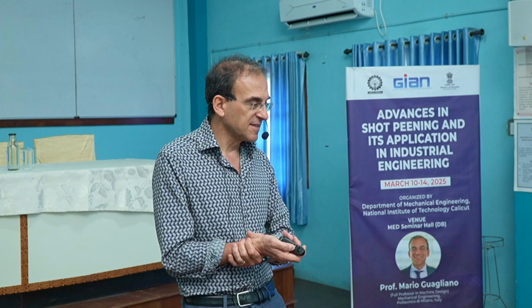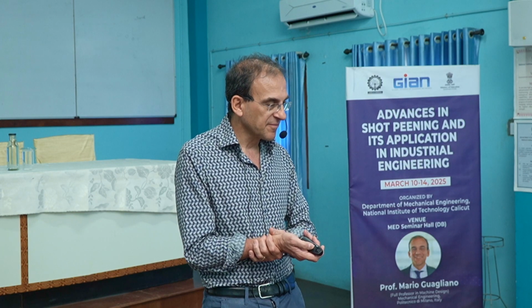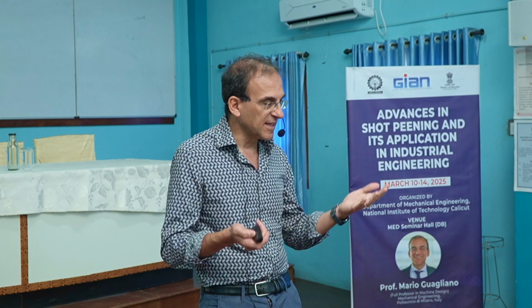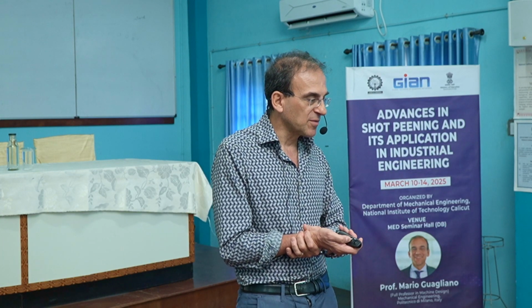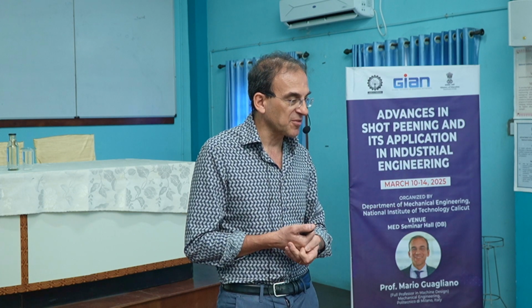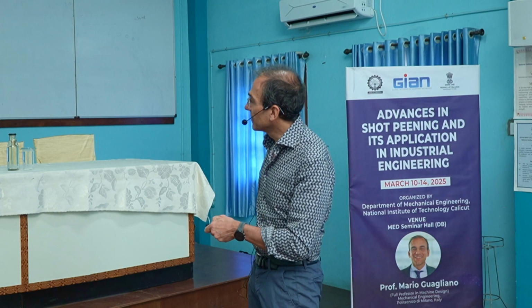Okay, there is another, the International Organization for Standardization standard, ISO standard, which also considers shot peening, calculation of tooth bending strength. So we are referring to bending fatigue in this case. In this case, they consider that shot peening is changing not only the residual stress, but also the roughness. And so they say that the surface roughness factor, Y_R, can be different if we are considering shot peened gears. But anyway, they recognize an effect of shot peening that is quite limited.